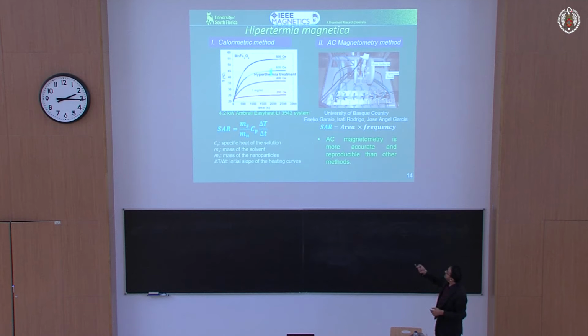So by looking at this, you can say that for these particles, under these conditions, about 500 Oersted field at the frequency of 325 kilohertz, in our case it's a fixed frequency power supply, is the ideal condition for hyperthermia. So this is how we determine the SAR, okay? What is the right SAR for this?